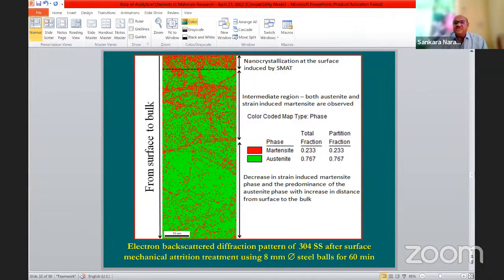So what happens is it confirms that nanocrystallization of the surface has occurred only at the top layer, and you can measure up to what micron it has. So with increase in depth, there is an increase in the grain size from the surface to the bulk. That confirms that by doing a SMAT treatment, it is possible for us to prepare a graded layer structure. Normally we cannot see this by other methods.